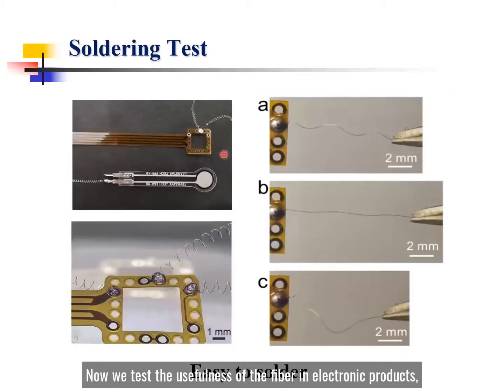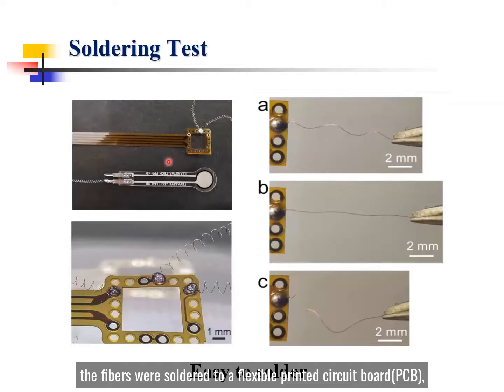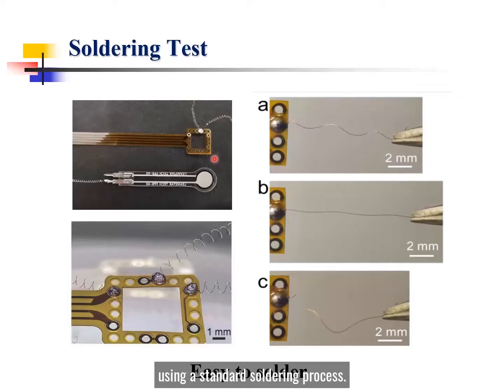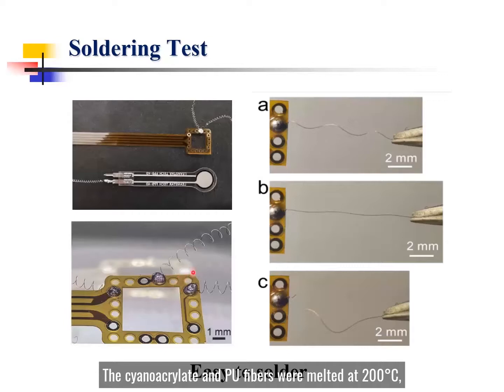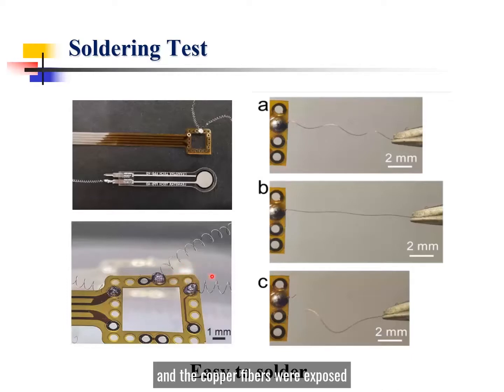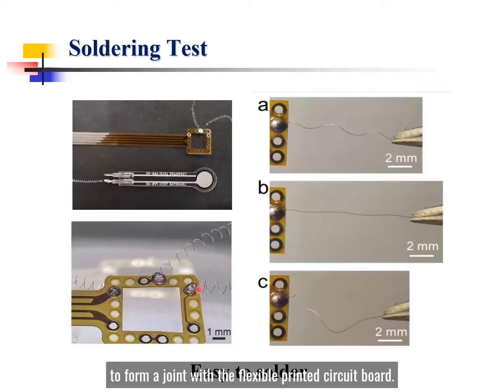Now, we test the usefulness of the fiber in electric products. The fibers were soldered to a flexible printed circuit board using a standard soldering process. The cyanoacrylate and the PU fiber were melted at 200 degrees Celsius, and the copper fiber was exposed to form a joint with the flexible printed circuit board.